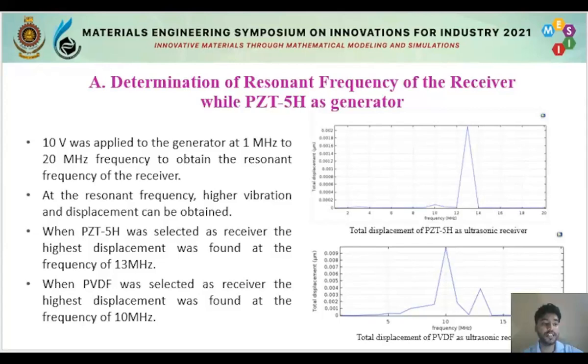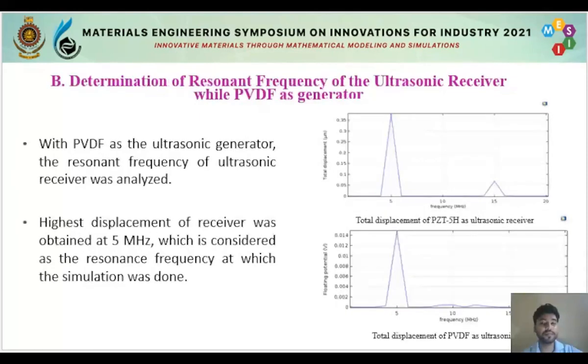When PZT5H was selected as a receiver, the highest displacement was found at the frequency of 13 MHz. And also, when PVDF was selected as a receiver, the highest displacement was found at the frequency of 10 MHz. The next is to determine the resonant frequency of the ultrasonic receiver while PVDF is the generator material. Here in the receiver material, the highest displacement was obtained at 5 MHz.